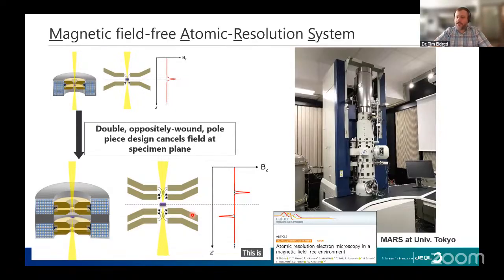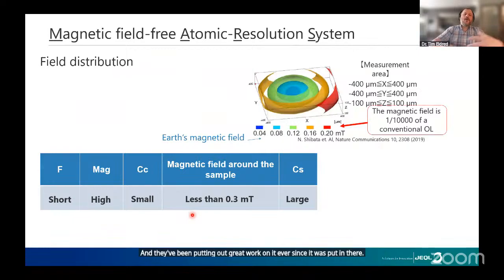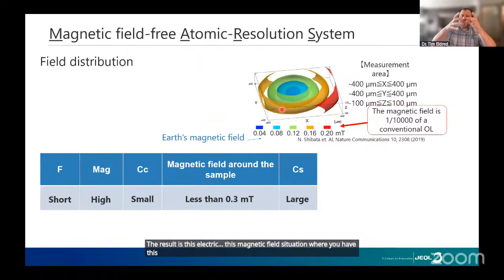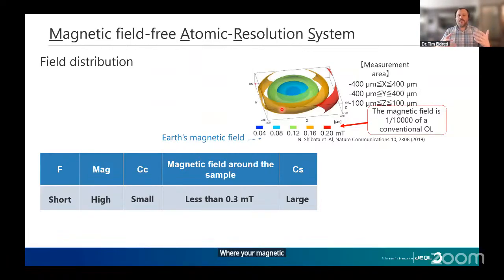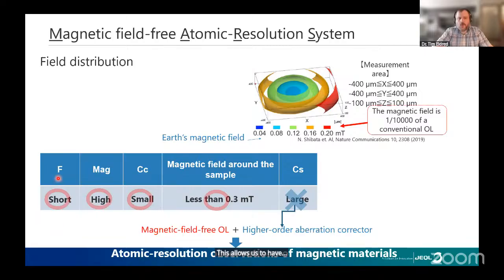This is the first MARS that is at University of Tokyo in the hands of Dr. Shibata, and they've been putting out great work on it ever since it was put in there. The result is this magnetic field situation where you have this eddy in the middle, where your magnetic field is on the order of, if not less than, the magnetic field experienced on the Earth. 10,000 times reduction in your magnetic field from a traditional instrument. This allows us to have short focal distance, high magnification, low aberrations, and low magnetic field around the sample.